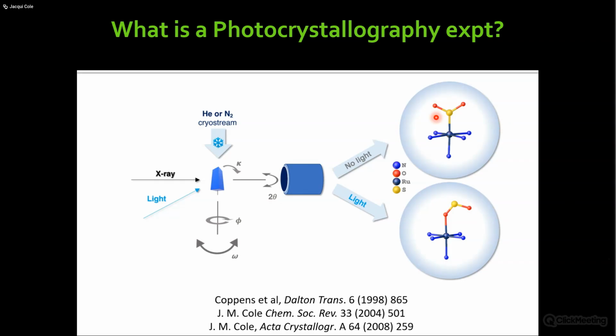And there it is. And then you will essentially do a second experiment while keeping the crystal on the diffractometer, keeping it cold. Then you apply light, and then you will maybe get, if you're lucky, a nice clean state of the light-induced species. It doesn't always happen like that, right? So in this case, now it's the oxygen-bound SO2 ligand isomer. All right, and then heat it up, and you'll hopefully get back to the dark state.